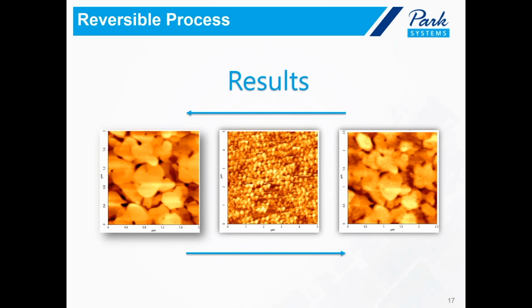So just to give you a summary on what we did in the experiment. First, we took a reference image, as you can see on the left image. Then we deposited copper particles on the gold surface, as you can see on the AFM image in the middle. And then we removed the copper particles back into the solution, and we got a surface which is as pristine as the reference image, indicating that, again, this process is completely reversible. This simple experiment, I just want to mention to you again, we have done using our new Park NX12, which is equipped with the EC-AFM option.